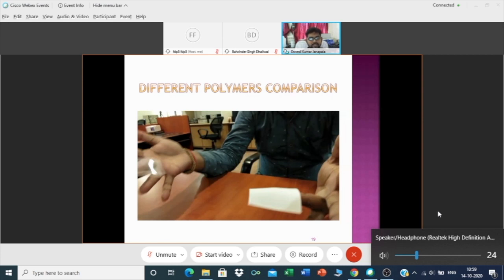The process is just like how I did with GO. You have to mix it, grind it finely, put it into solvent, and disperse it using sonication. Then you put it into the polymer, do the hand stirring, and again degassing, pouring, baking and peeling off.